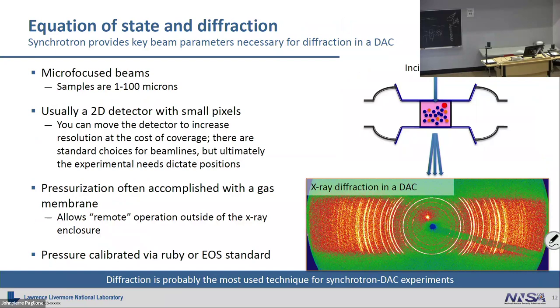Like I said, the workhorse of the synchrotron is probably X-ray diffraction. I haven't done any significant analysis, but I would bet that 4 out of 5 pressure papers is a diffraction paper, or has diffraction in it at this point. It's very rare to find a paper where someone discovers anything new anymore at below 100 GPa that doesn't have diffraction. So it really is a workhorse.